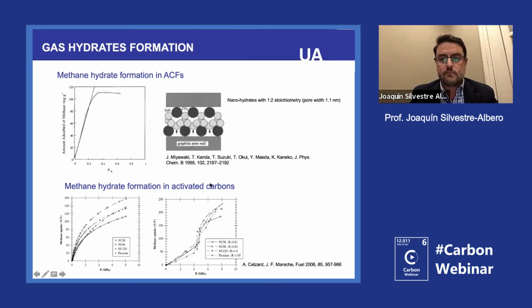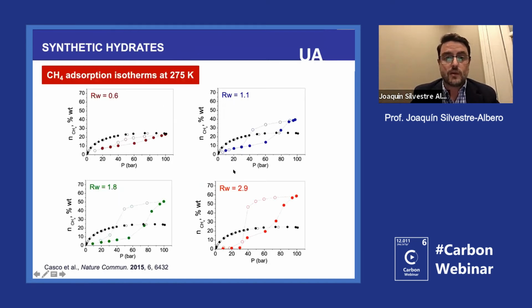Also in France, there is a big community of scientific groups working with gas hydrates. And this is a paper from the group of Alain Celzard from 2006. The same, they were measuring the methane isotherms in the dry material, so you have the type 1 isotherm. And then when they applied the same isotherms in a system with pre-adsorbed water, they had this very strange isotherm. At the beginning, you have a blocking, and then at a certain point, you have a jump, at 4 megapascals. So that was a confirmation that something is happening in the system. You reach a point, around 3-4 megapascals, where you have a large improvement in the adsorption capacity of methane. So these were the papers that we were using as inspiration for our research.